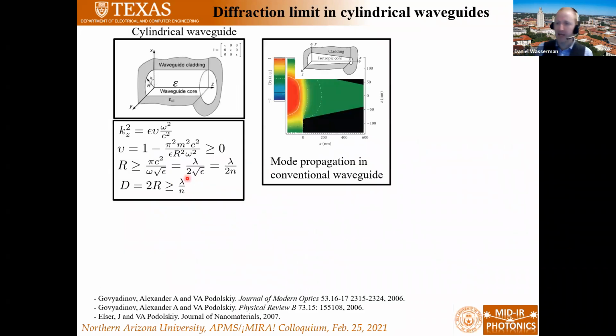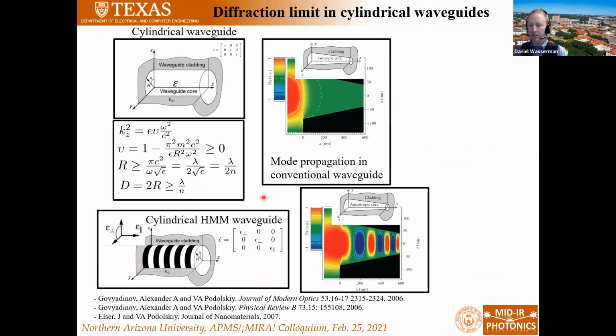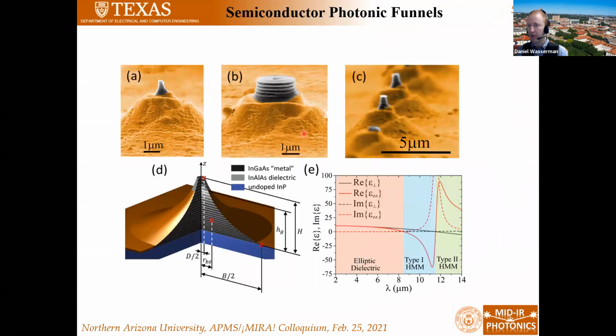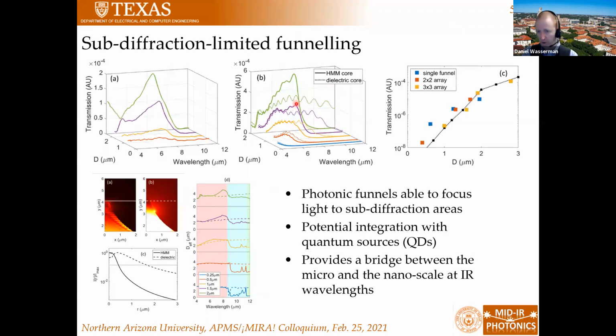And I know I'm running out of time, so I'm just going to skip over this, but I do want to say that one of the things we've done recently is we've taken our hyperbolic metamaterials and we fabricated them into funnels. And it turns out that when you have a hyperbolic metamaterial, you've basically beaten the diffraction limit because of your anisotropic permittivity. You can confine a mode to ultra sub-wavelength dimensions. So what we have here is essentially a device where the funnel takes a metal-clad waveguide and brings it down to sub-diffraction limited thicknesses or areas.